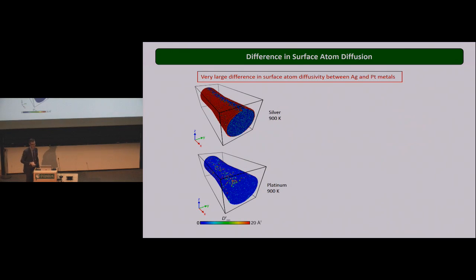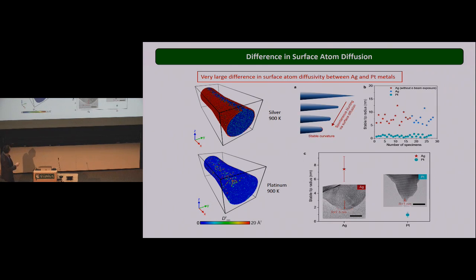So very promising material. And my last slide today is just to explain why platinum didn't behave like this. The main reason is that with platinum, in simulation, we see here that surface diffusion is very limited when you compare at the same temperature, because the melting point of platinum is much higher than silver. So at the same temperature, you experience much less surface diffusion with platinum. And surface diffusion is critical to make this process happen. If you do not allow for the step to diffuse, then you will create a shear band.